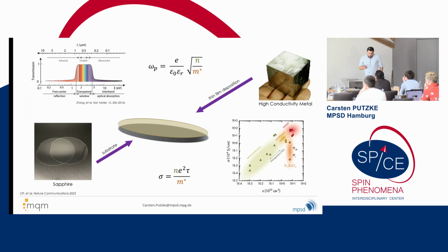But what we actually found in this material is something, if you think of a layered material, you have two kinds of conductivity. You have the interlayer conductivity, and you have the in-plane conductivity. And I just showed you that in the plane of palladium cobaltate, we're basically ballistic. We have a mean free path of 20 micrometers, very long, right? But out of plane, when you look at the interlayer hopping, that's very different, and the conductivity here, in this case strontium ruthenate, is about 100 times lower.